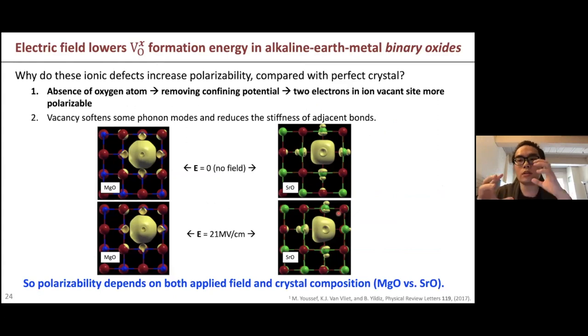So why is the dipole moment, or the polarization, of the defective cell higher than the perfect cell? Here, I'm showing the electron charge density in the vacant site. This is magnesium oxide. The top row is no field, and the bottom row is around 20 megavolt per centimeter. Visually, for magnesium oxide, the electron charge density changed a little bit, but it's not that obvious. However, for strontium oxide, you can already see clearly that the shape of the electron cloud is being polarized into one direction, and it is not symmetric anymore.